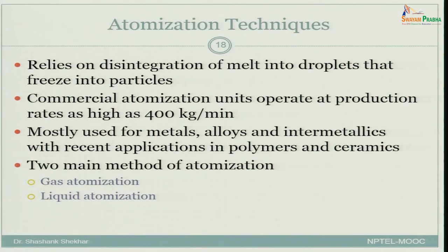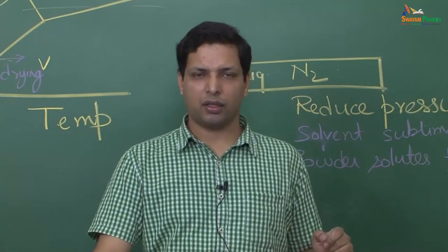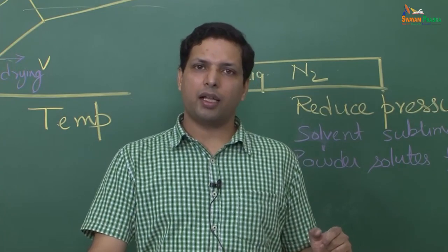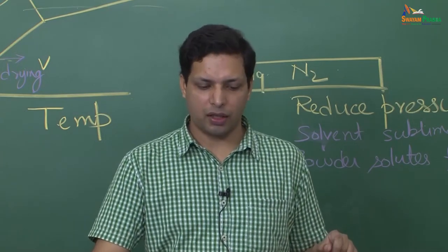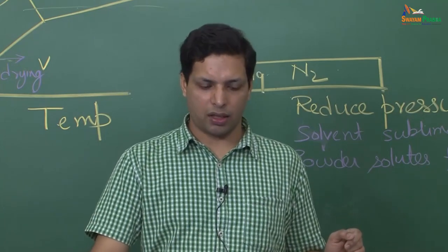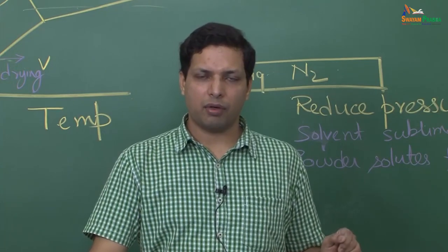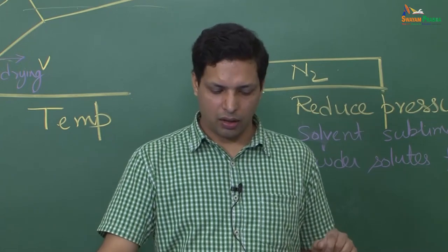Let us get to some more fabrication techniques. One of the most well-known is the atomization technique. In this process you disintegrate a melt — you melt the material and then disintegrate the melt into very fine droplets. Once you have those fine droplets you freeze them and you will get very small particulates. Using this method people have even been able to get nano-sized powder, since it is a brute force method where energy is applied through gaseous or liquid state, giving gas atomization or liquid atomization.